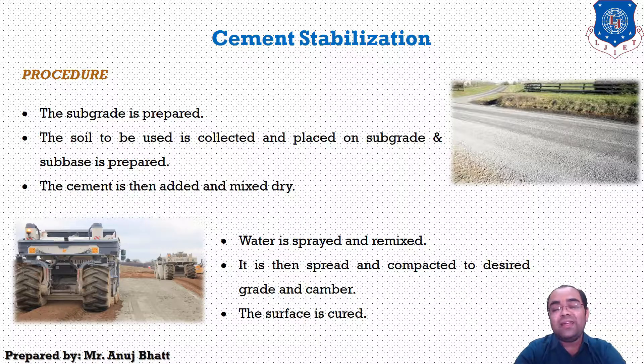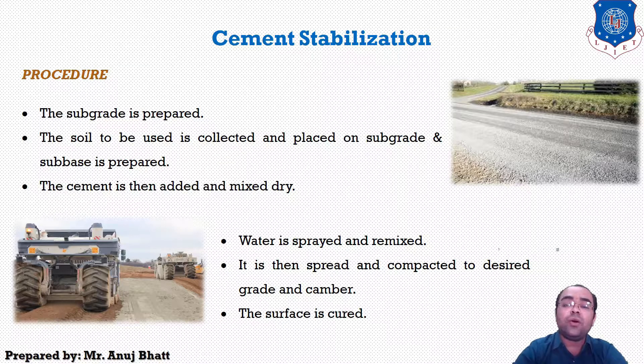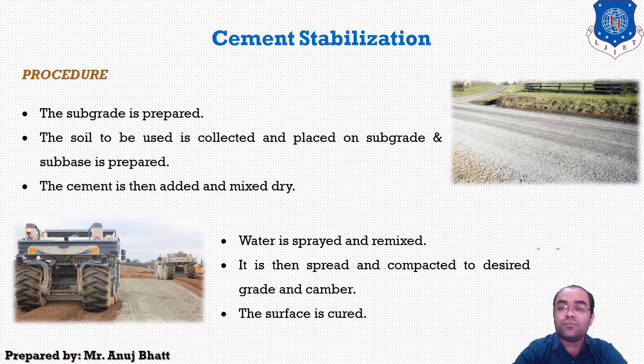The mixture is spread and compacted to the desired grade and camber. The surface should then be cured by preventing moisture from escaping — this can be done by covering with paper or moist soil. This concludes the cement stabilization construction process.